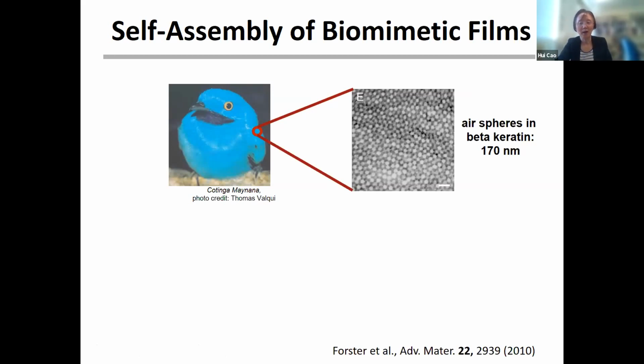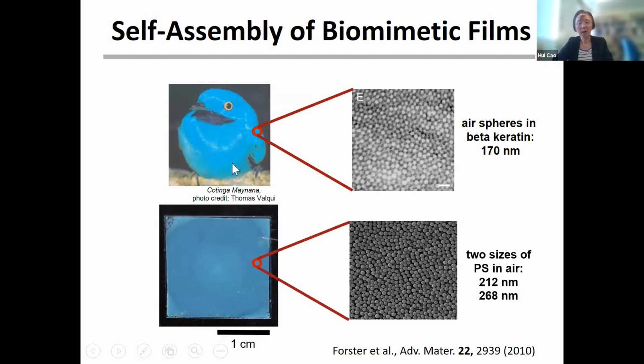Now let's try to mimic it to generate this. This is in collaboration with Professor Eric Dufresne's group. We use two different sizes of polystyrene spheres, like very small plastic spheres, about 200 nanometers in diameter. Then we mix those two different sizes of polystyrene spheres in solution, and then we spin coat it on a glass substrate. Then we can see a really blue color from this film.